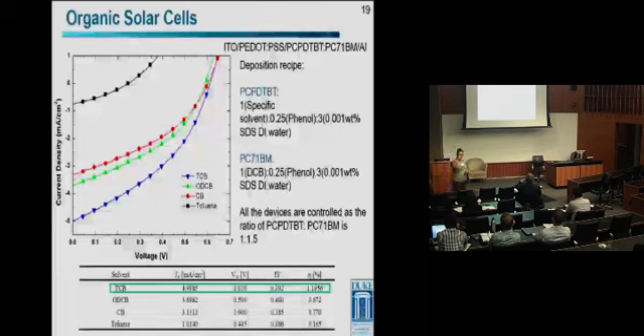The same way we saw those very different morphologies in the TEM images I showed before, when we looked at the solar cells that go along with that, we saw a very big variation in the solar cell power conversion efficiency just by changing the primary solvent. And this parameter space is wide open. We've just begun trying to understand this better and what it means for the organic solar cells. So we went up to about 1.2% power conversion efficiency just by changing the primary solvent.